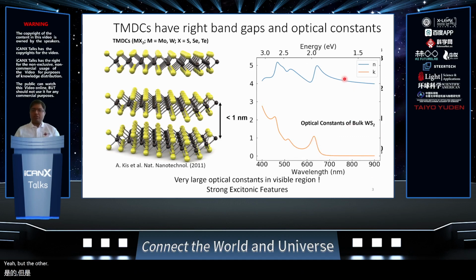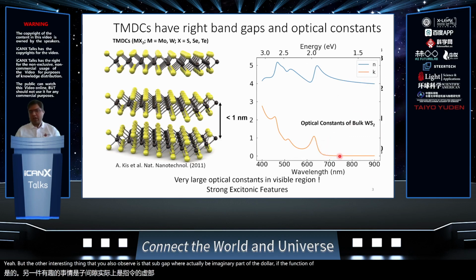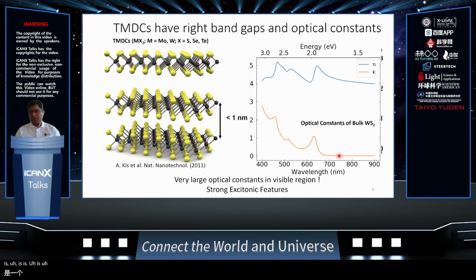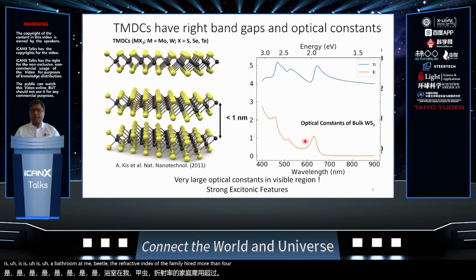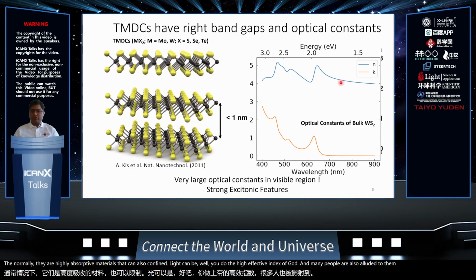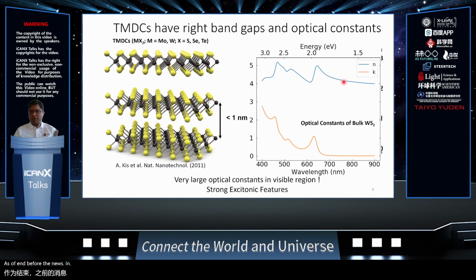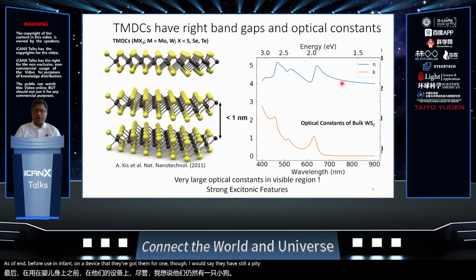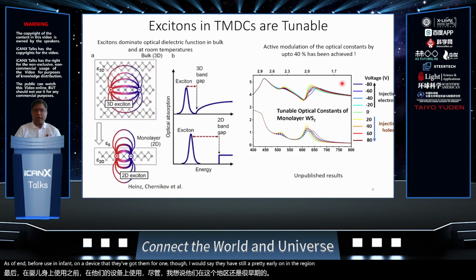The other interesting thing you also observe is that even sub-gap, where the imaginary part of the dielectric function, or k, is approximately 0, the refractive index is extremely high. It's more than 4. So not only are they highly absorptive materials, they can also confine light extremely well due to the high refractive index sub-gap. Many people have also alluded to them for use in photonic devices as waveguides and so on, though I would say they are still pretty early in the research stage. Okay, so why were we interested in them?